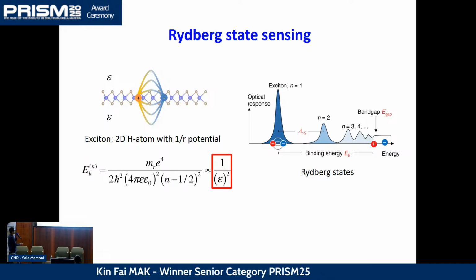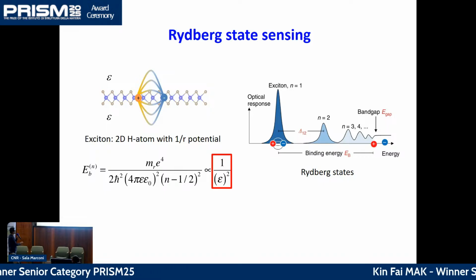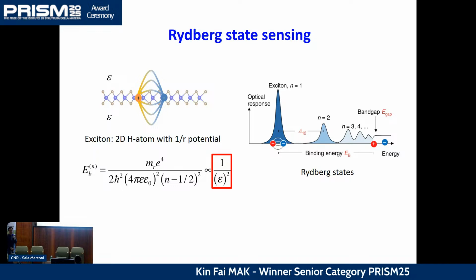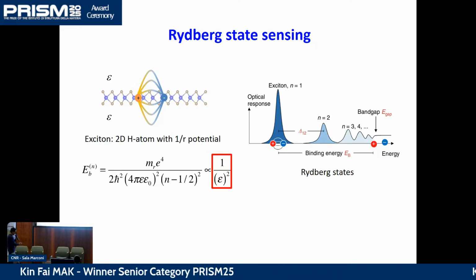And this is a schematic absorption spectrum of this type of material. You can see the 1s Rydberg state, 2s, 3s, 4s, and so on and so forth until you hit the band gap here. The difference between the 1s energy and the band gap gives you the exciton binding energy. And we are talking about half an electron volt of binding in this type of material.